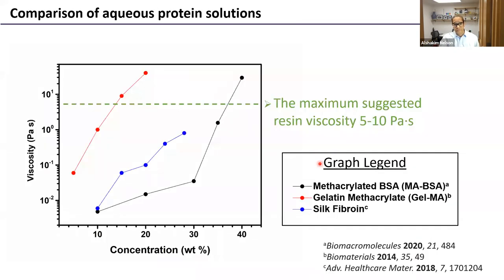All right, so again, the important feature of using BSA is that it has great solubility. And so if we compare concentration of protein to the viscosity of a solution as you increase the concentration of a protein, comparing three different proteins here. So gelatin methacrylate, which is commonly used for different photopatterning processes. You'll see that very rapidly increases its viscosity, but that's because it's forming these anisotropic structures. Silk fibroin that's been digested also will increase as well, although not quite as rapidly as gelatin methacrylate. But here with the methacrylated BSA, we can quite comfortably get to about 30 weight percent and maintain a pretty low viscosity. This green line here represents the maximum suggested viscosity for a resin. Although in our hands, we think that lower is better, and 10 might even be getting to be too high.